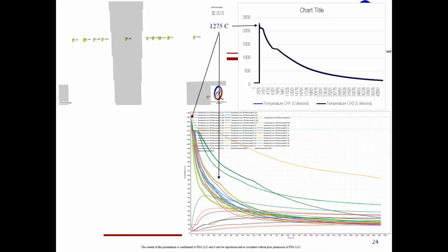Actually, by the time we got the metal into the sprue, we were around 1275, and that matched fairly well with our simulated conditions. We put some thermocouples in the metal as well as in the mold.